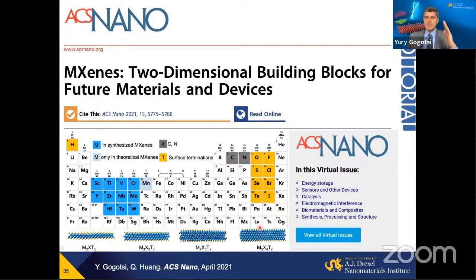Second, you can look at the MXene structures. It's a 1-1-1 slice of the sodium chloride cubic lattice. So you get a surface which is actually not usual in nanoparticles, nanocrystals that would grow in a different configuration. So you get the entire surface. Moreover, you can have materials where, for example, you can embed platinum or gold in vacancies of the transition metal in the surface, making single atom catalysts. And you can take a solid solution and consider, for example, an embedded atom, say, of tungsten in titanium carbide to be like a single atom catalyst. So I think you get an idea.